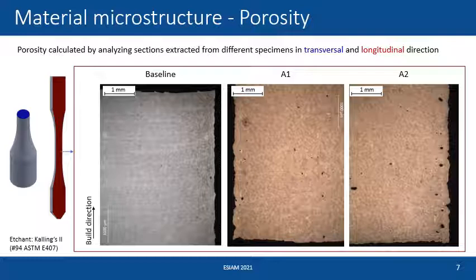Here on the right part of the slide, you can see a comparison of three sections in longitudinal direction from baseline parameters, A1, and A2 parameters. It's evident that while in the baseline condition the porosity is almost absent, we see only some small pores due to gas entrapped. When we move to productivity-oriented process parameters, the porosity increased. In the A1 it is greater, in the A2 it is still greater than the A1 condition.